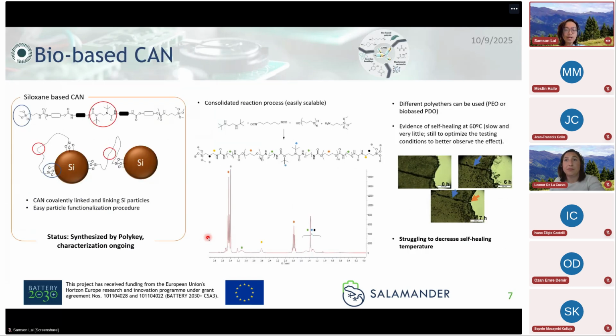But we did end up designing a sort of a new polymer using a siloxane-based chain, reasoning, thinking that maybe these polymer chains are just too mobile and they're not really attached to the silicon. So we thought, let's add this kind of siloxane functional group and then make it so that it's covalently linked to these particles. And then we also have this self-healing aspect, which can then kind of connect these two particles together. So we were able to do that.